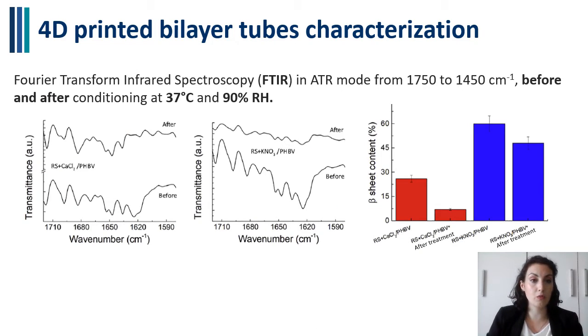Then the tubes were characterized by FTIR, before and after conditioning at 37 degrees and 90% relative humidity. The analysis revealed that the addition of potassium nitrate increased the amount of beta sheet. This is due to the increased salt presence that acts as a cross-linking agent. Differently, the treatment in the climatic chamber slightly decreased the amount of beta sheet.